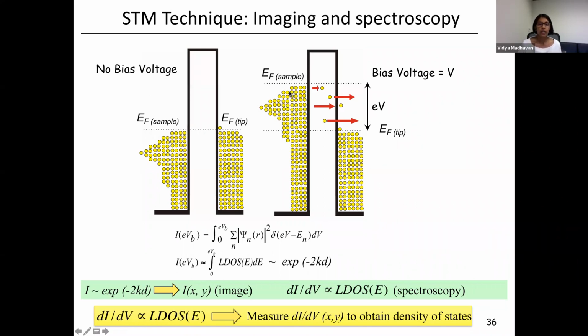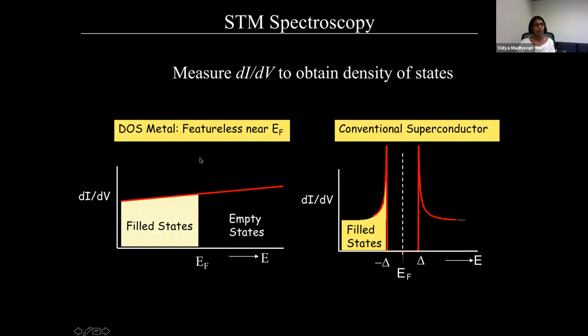And you can see even pictorially that this tunnel current must be proportional to the integrated density of states of both the sample and the tip. That means that by differentiating, dI/dV, you should be able to measure the density of states of the sample. So what do we expect? For example, if you have a metal, then you expect a very flat density of states. So if you were to measure dI/dV, you would simply measure a straight line going across the Fermi energy. For us, the Fermi energy is always 0 volts, so 0 bias. Whereas if you measure the density of states of a conventional S-wave superconductor, you would see no states near the Fermi energy up to the gap value of delta. And at the gap value, you would see these sharp coherence peaks that tell you what the magnitude of the gap is. So this is what a superconducting spectrum should look like, shown in red here.